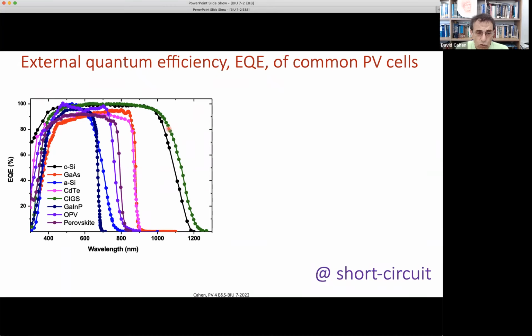I can also look at something, the external quantum efficiency, which essentially is the current as a function of monochromatic illumination. And ideally, I would like it to be a rectangle, from wherever the sunlight starts to reach till the cutoff. And the best cells get close to it. It's difficult to see maybe in this very busy picture, but the champion is someone called gallium indium phosphide. But it has a very high energetic cutoff.